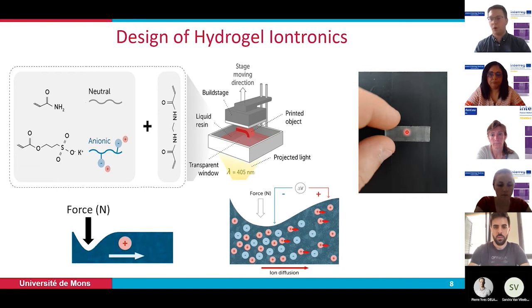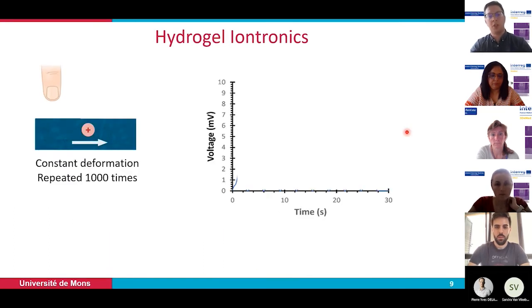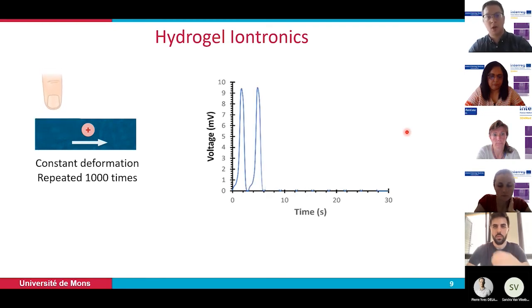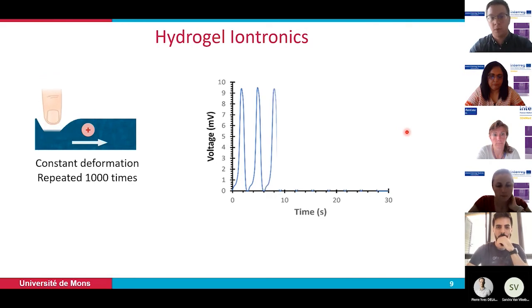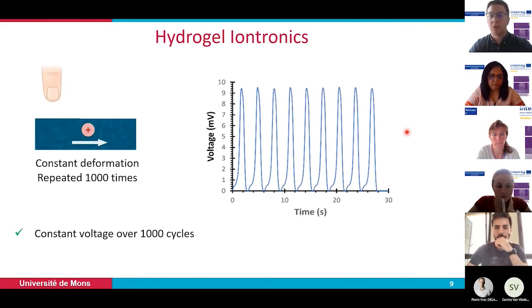But okay, you have your system. You need to know, can you rely on the results of your material? So first of all, we apply a constant deformation repeated 1,000 times. What we need is a fast, quick response, and a constant response over time and over several cycles of deformation. So we apply this deformation, and what you can see is that we have a direct response in terms of voltage to this deformation. And what we can also see is that the voltage is completely constant over different cycles. So now we have a material that works perfectly, but okay, this is for a constant deformation.